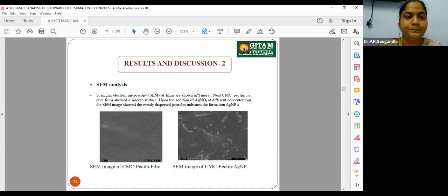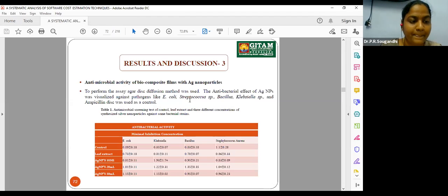So coming to SEM analysis, SEM is scanning electron microscopy. Here, if we see, there are two images present. The first image is of the CMC pectin film, that is, CMC pectin film without the presence of any nanoparticles. Whereas the next image is CMC pectin with the presence of silver nanoparticles. So we can see the difference: the first picture is very clear, and in the other one we have the images of silver nanoparticles.